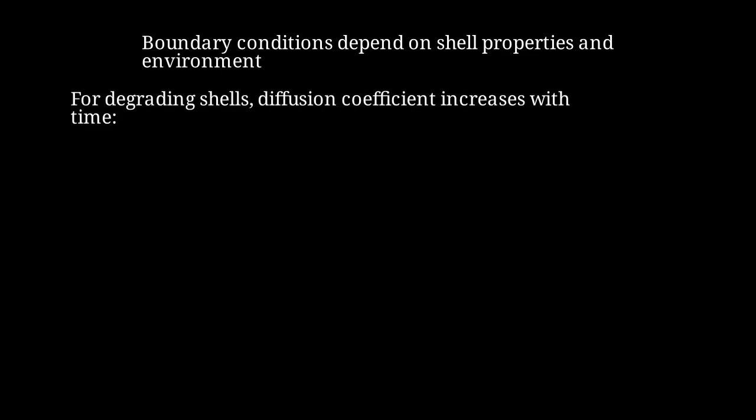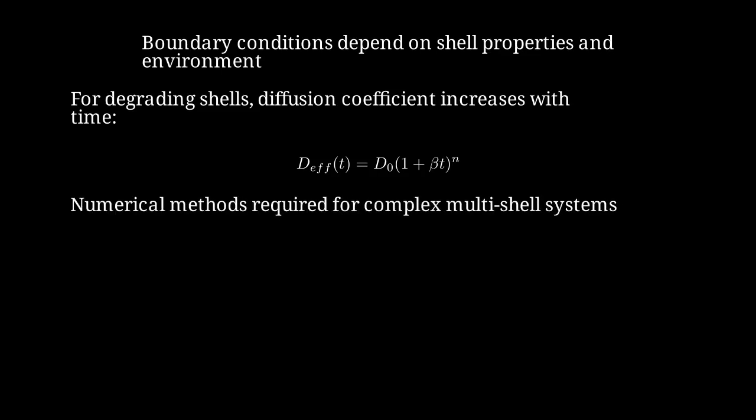Boundary conditions at the shell interfaces depend on partition coefficients, shell permeability, and external sink conditions. For shells undergoing degradation, the effective diffusion coefficient increases with time as pores form and grow. D effective of t equals D0 times 1 plus beta t to the power n, where beta and n are empirical parameters describing pore evolution. For complex multi-shell systems with multiple stimuli, analytical solutions are not available and numerical methods such as finite element analysis are required. Let us briefly discuss experimental techniques for characterizing microcapsule properties and release kinetics.